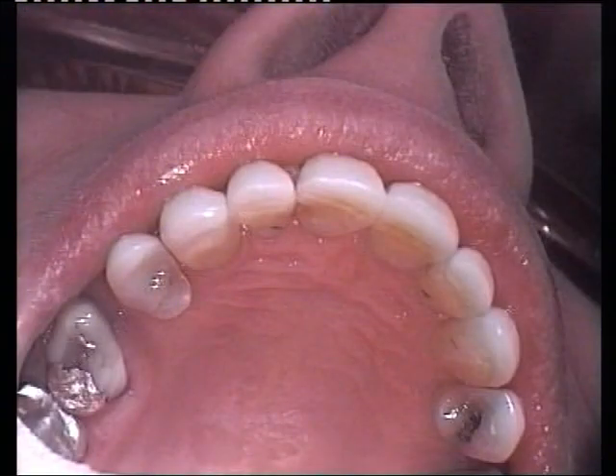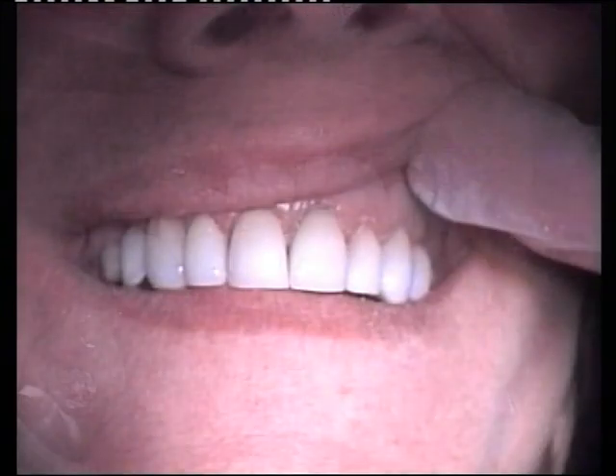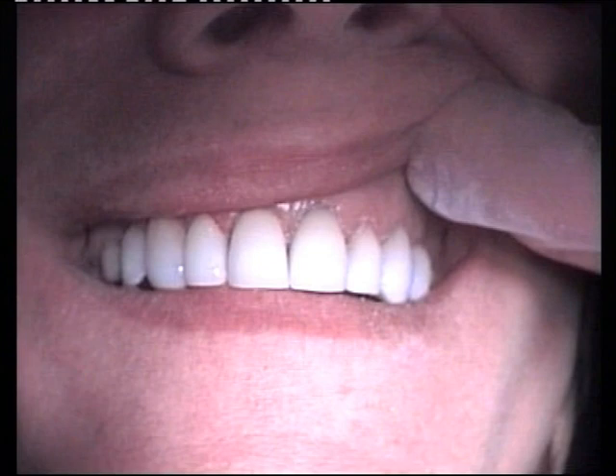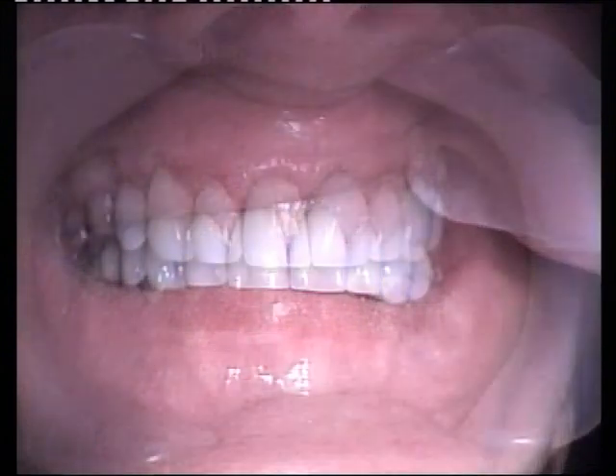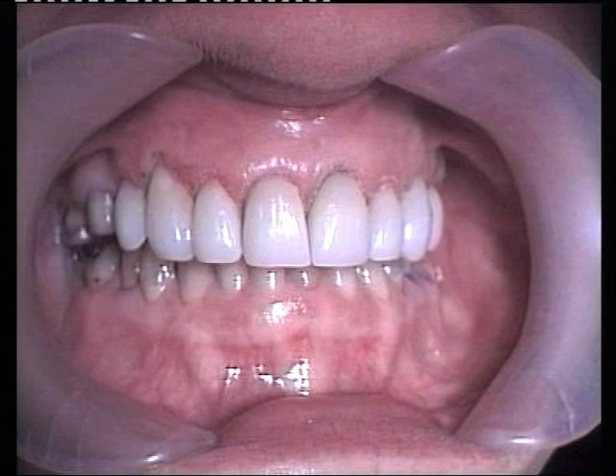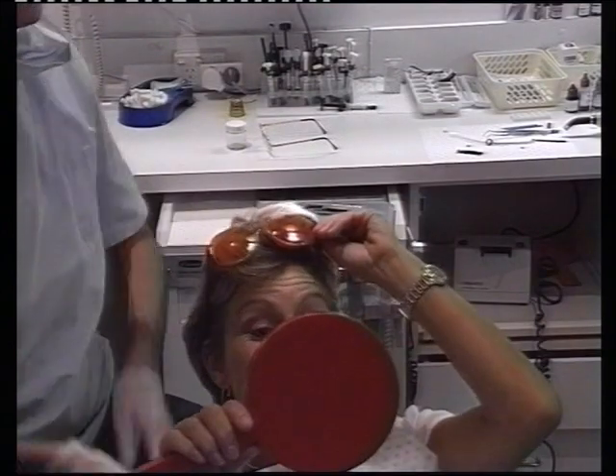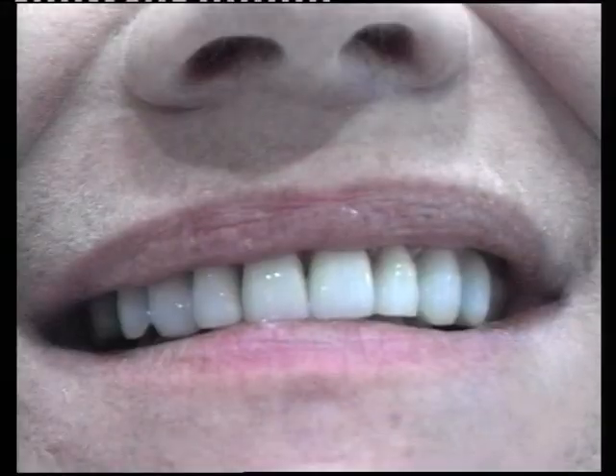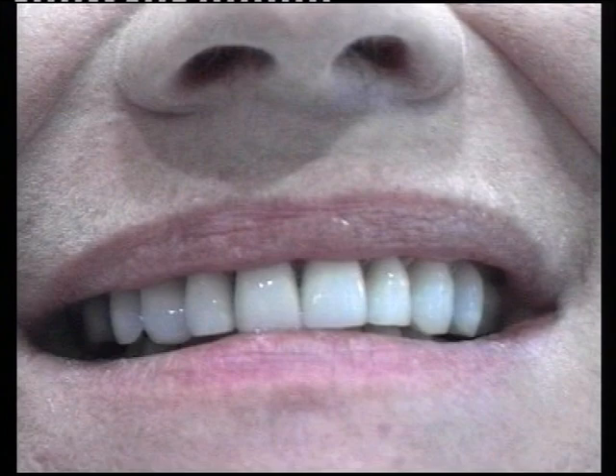An incisal view confirms the regularity of the laminate contours. From the labial aspect, the uniformity of the laminates is evident. There is minimal trauma to the gingival tissues, and after 2 hours, the white eschar from the trichloroacetic acid has completely disappeared. This is the moment of truth. Most patients are elated with the end result, but expect an occasional unusual reaction because of the significant change in body image that has occurred.